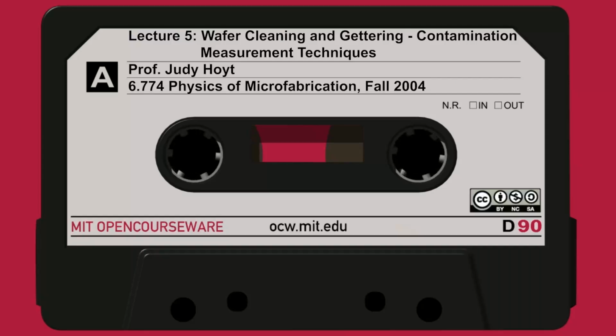And in fact, we want to keep it as low as possible so our threshold voltage isn't moving all over the place and we're getting ideal characteristics. And what we do is, after we do an oxidation, the last high temperature step is typically some kind of forming gas anneal. And after annealing, this DIT goes down by about 2 orders of magnitude. So you notice the last step in a MOSFET or in an MOS flow, if you've done it, is to do an annealing in forming gas, which has hydrogen in it, at about 450 or 500. And that takes this DIT from up here all the way down to here, to a level that's tolerable for the device to operate.